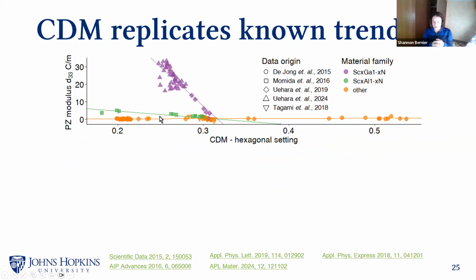The clustering is a little bit different, but we still see that the different materials families come out in different ways, and that an increasing amount of cubicness leads to a higher piezoelectric modulus. So this is a replication of results. And then we wanted to talk about, with this example, what happens if you choose a different unit cell.